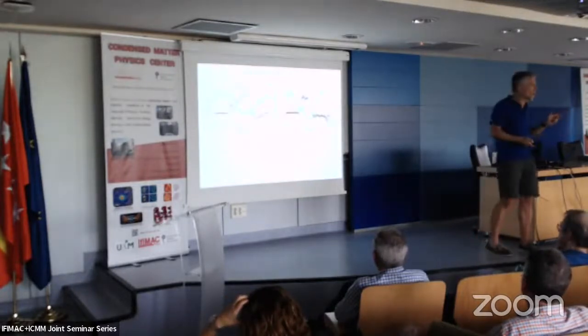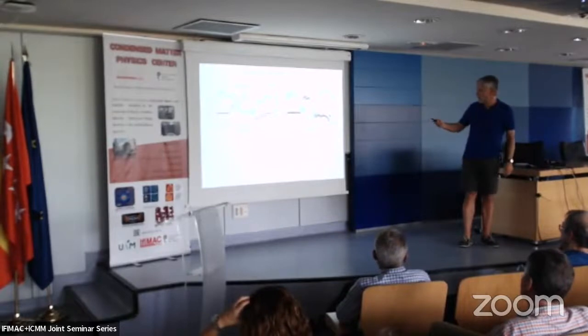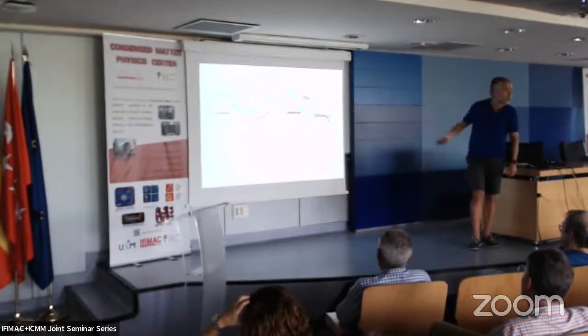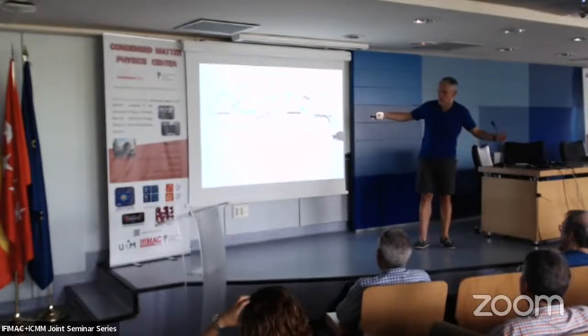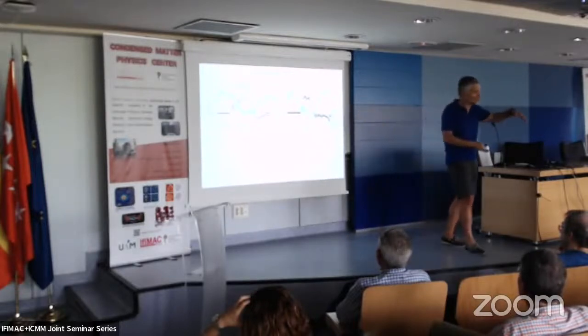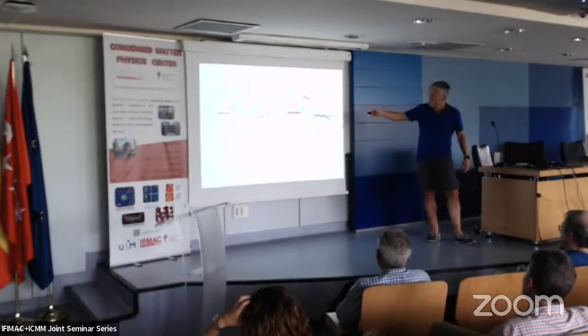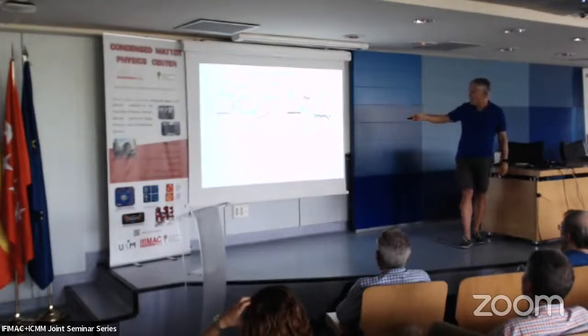So we use two kinds of tips in order to check what is the change of the microenvironments. We use insulator silicon nitride and gold covered tips. So this is what happened in the case of silicon nitride. This is what happened with gold. With silicon nitride, you see that when you touch the virus right here in this corner, nothing happens, as I explained before. However, when you start breaking the virus, you start seeing the steps in the force, which means that you are breaking the virus. In that moment, you see that the light starts going down. However, in the case of gold tips, you see that the light starts going down well before you touch the virus with the tip. So it's happening before. You see that this red line is marking the place where the light starts going down.